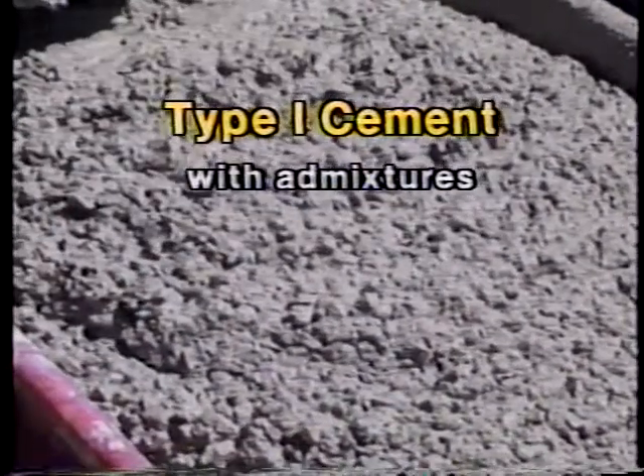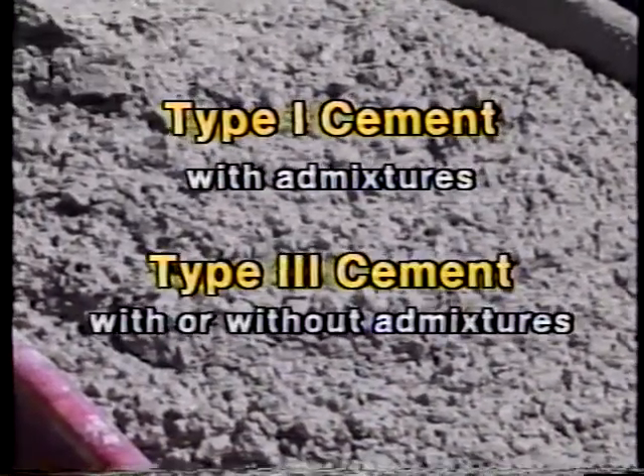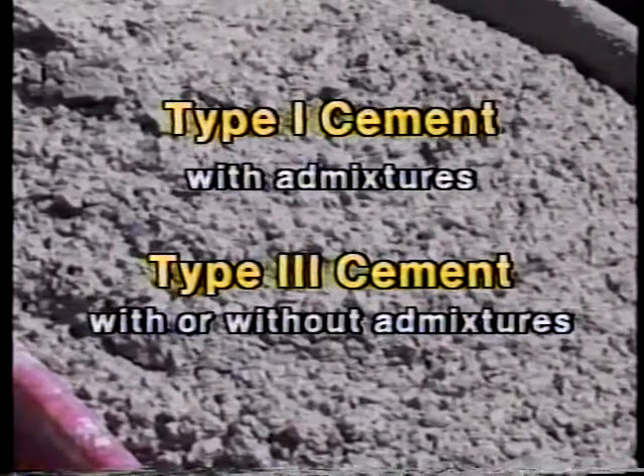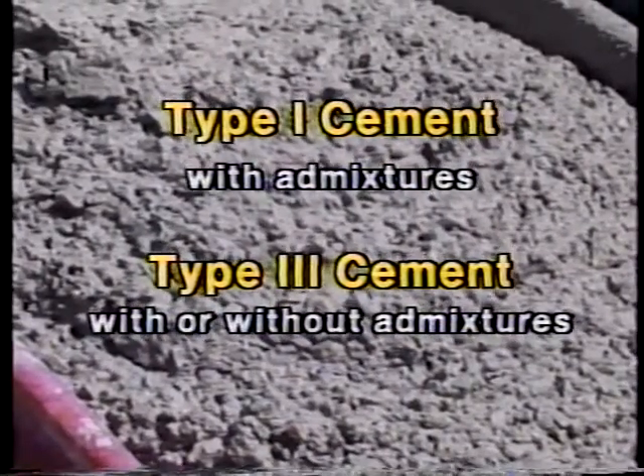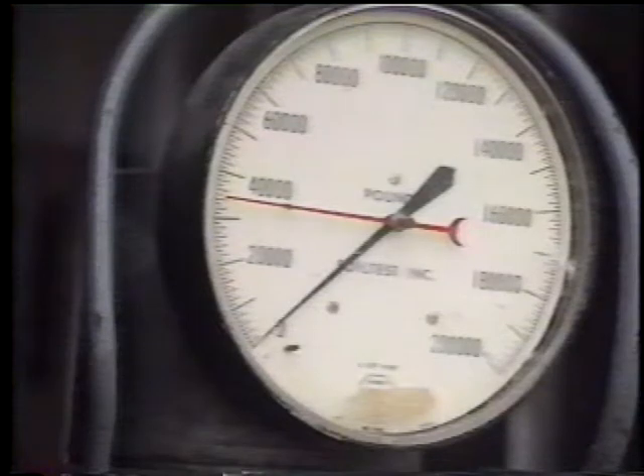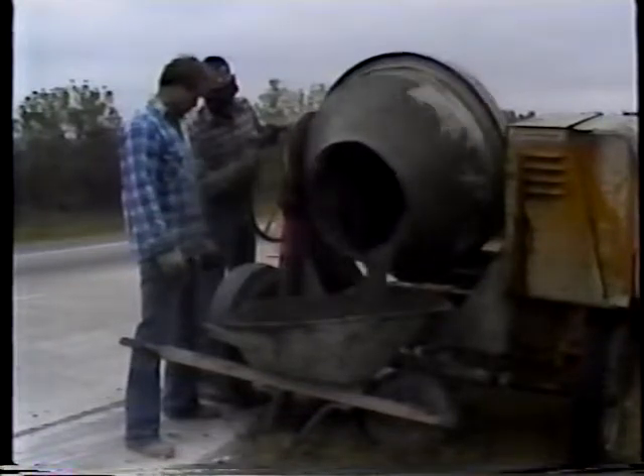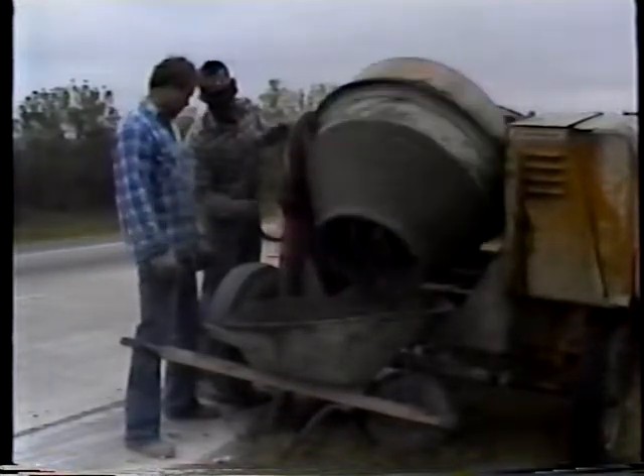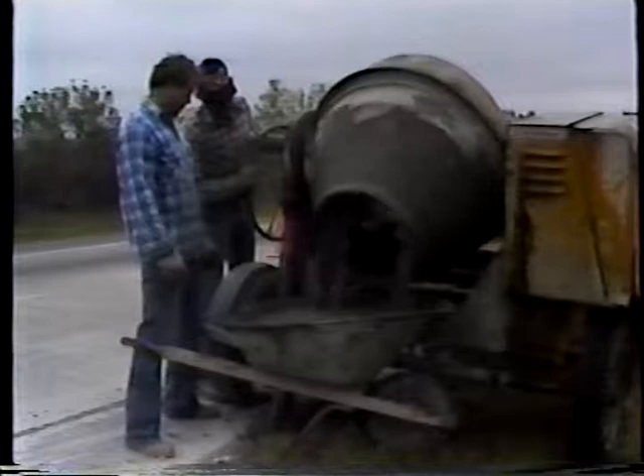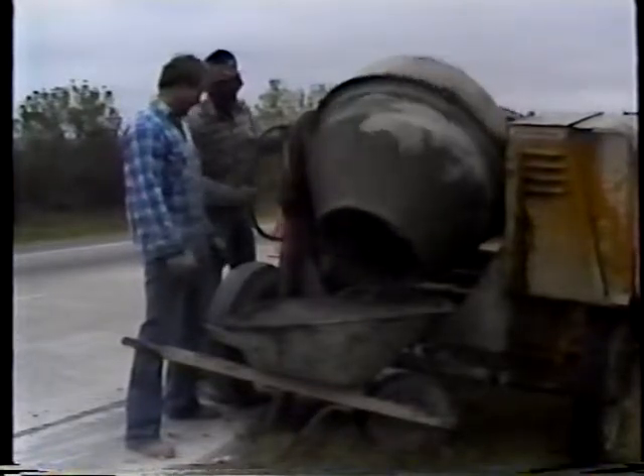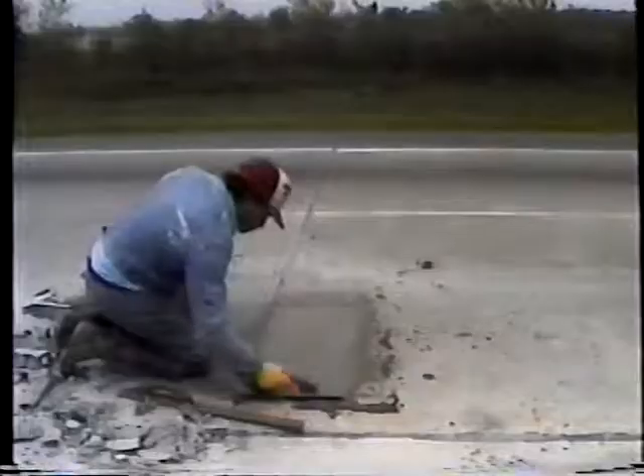High early strength concrete for rapid repairs contains either type 1 cement with admixtures or type 3 cement with or without admixtures. Both can attain compressive strengths in excess of 3,000 psi in 24 hours. A number of proprietary materials may also be used. For best results, it's important that the manufacturer's guidelines be followed closely.